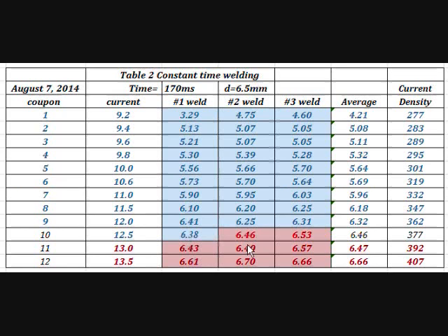This is very interesting because the professors always assume there is a weld schedule that gives you fusion welding and yet no expulsion. If there is such a weld schedule, it has to be between this point and this point, right in the middle. Since this whole coupon number 10 is welded with the same schedule, 12.5 kiloampere, 170 milliseconds, there is no possibility that a weld schedule between this one and this one can give you a fusion but non-expulsion weld.